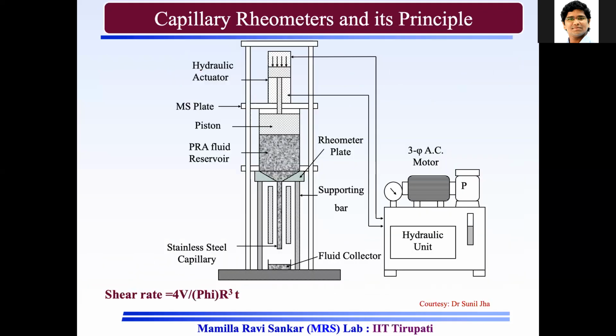For example, in my condition of abrasive flow finishing, I use our own system to measure the shear rate. How to measure? There is another variety of rheological characterization that is called capillary rheometry, or capillary based rheological characterization. What you do in this is, you make a chamber where you put your fluid and you apply your extrusion pressure in your setup itself. Abrasive flow finishing you have seen, so you can apply it and you can collect the discharge.